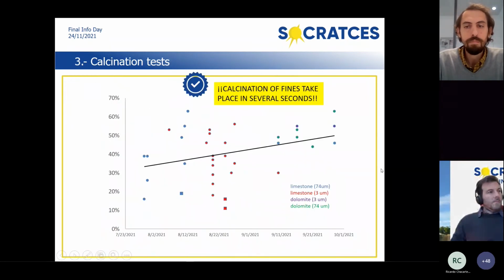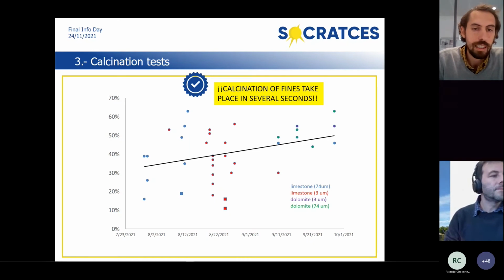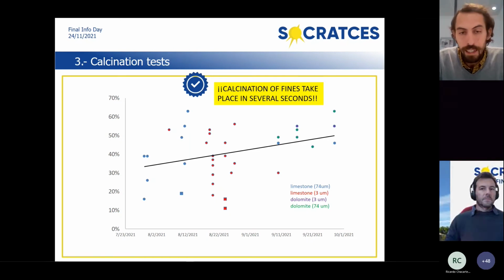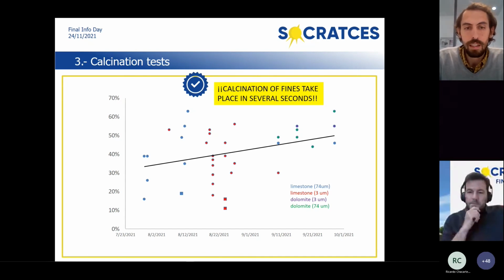Please, Juan. The same for the calcination. We have developed a lot of experiments for calcination reactions with several calcium oxide precursors, such as limestone or dolomite, for several reaction conditions, temperature, pressure, and for different particle sizes of the materials. And we are observing and demonstrating that we are obtaining calcination of fine particles in just some seconds. We are observing also that the best performance for the reaction, the best reaction extents, occurs for particle size around 70 microns, instead of lower size particles, which are more difficult to manage.